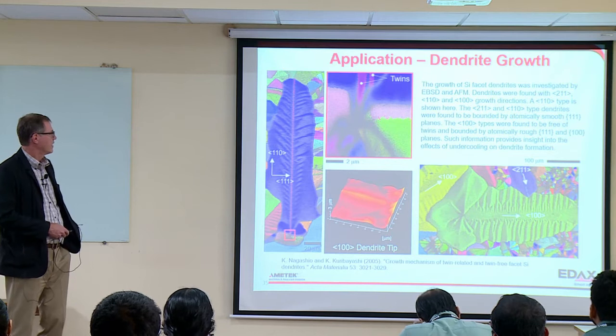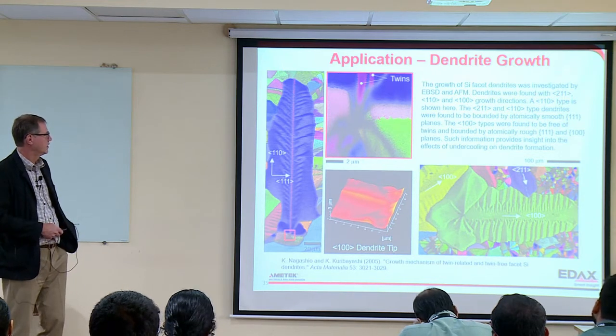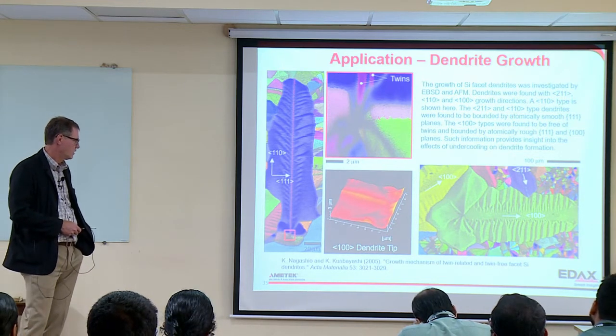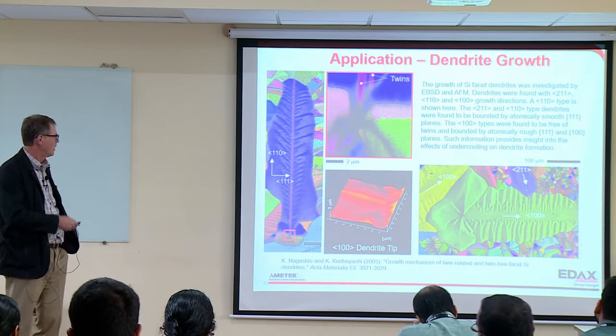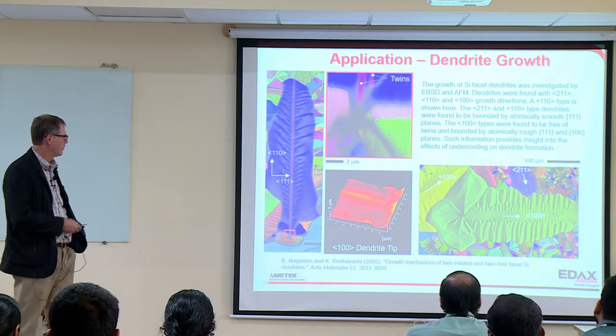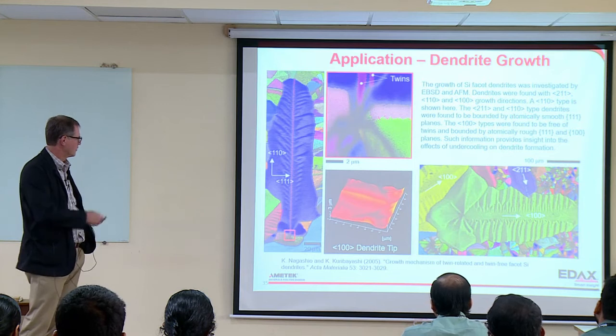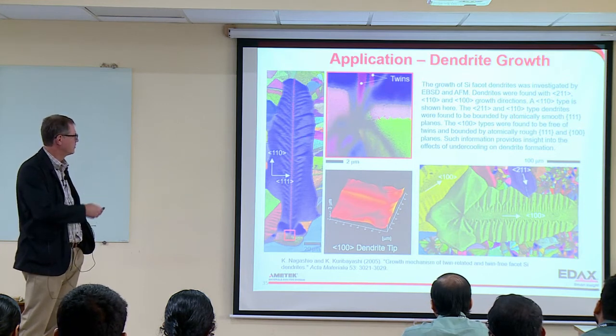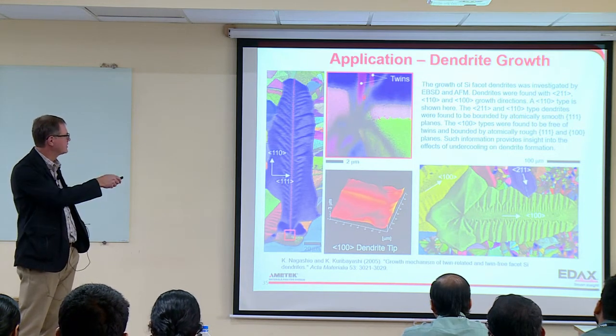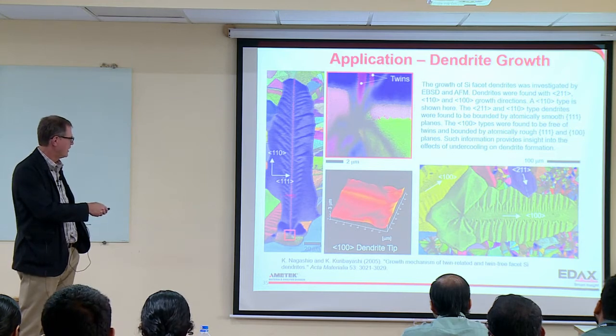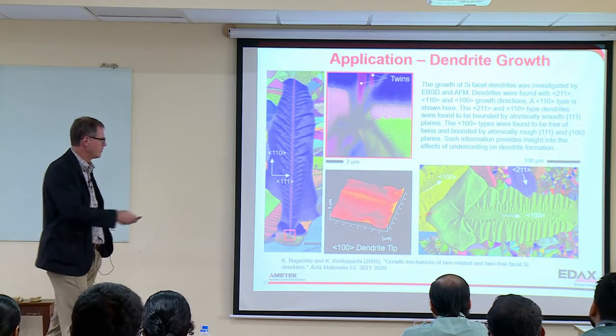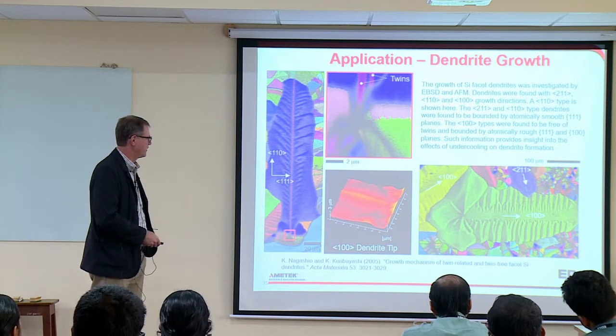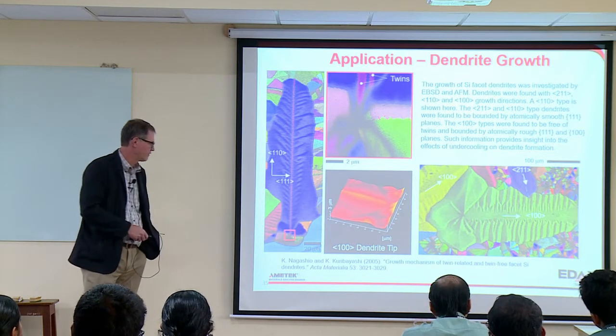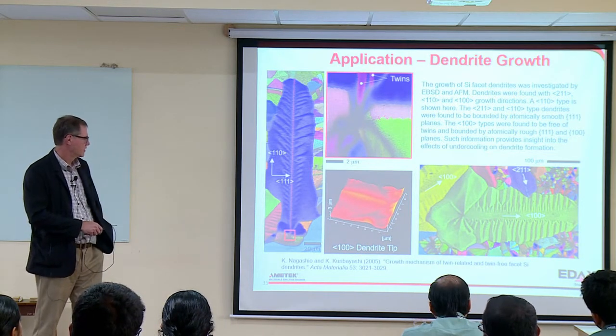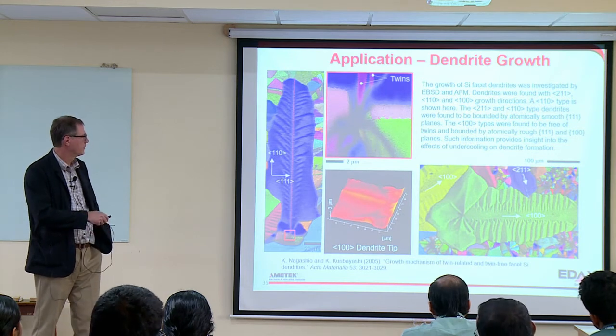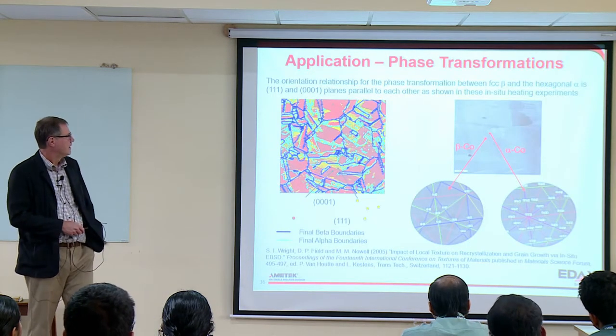Here's another example. This is dendrite growth in silicon. And beautiful images from the microscope here, and you can see some interesting growth of a twin relationship in this dendrite. There are actually two twins here, but this isn't high enough resolution to see both. So this just shows various growth and how they interact, and they compared those with AFM measurements. Very nice study that's getting pretty old now, but still good.